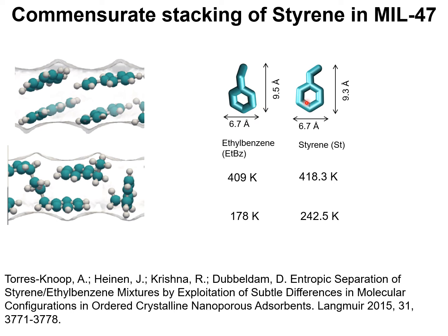The difference between styrene and ethyl benzene is that styrene is a flat molecule, and within the 8.5 angstrom lozenge-shaped channels of MIL47, we have a commensurate face-to-face stacking of styrene molecules, whereas in ethyl benzene, the side chain, the ethyl chain, is not in the same plane as the benzene, and the stacking of ethyl benzene within the channels is less efficient.